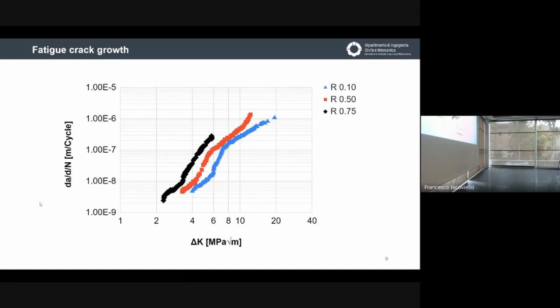These are the results compared across the different load ratios. You can see that the values of the threshold decrease with increasing load ratio. The high values of the ratio are very different, just a little bit more.